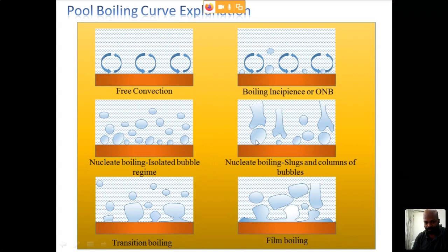And when this condition becomes so harsh that the vapor completely covers the surface, a layer of vapor forms between the liquid and the solid surface. This restricts the heat transfer from solid to liquid, and that's why the temperature of the surface increases to a very high value, and suddenly the surface can burn or fail. That's why this condition is called critical heat flux. That means it's very critical, and any system should not be operated at that point or above it.